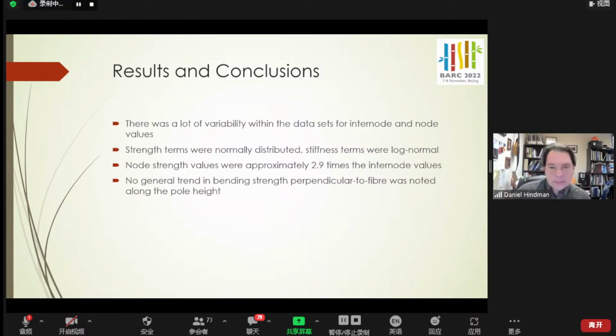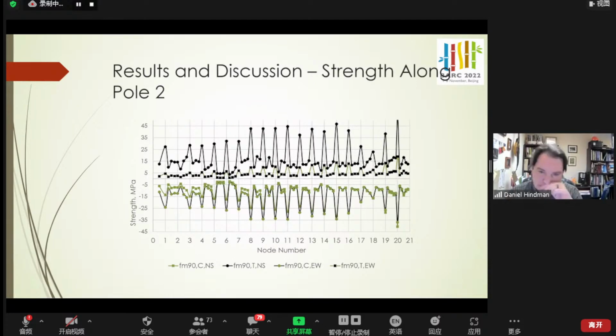And we did not really see a generalized trend in bending strength perpendicular to fiber along the pole height. If I go back to that image, and if you look at, for instance, the black circles, starting on the left-hand side of this graph would be the bottom of the pole, and the right side would be the top of the pole. There may be a generalized trend, but you can see there's actually more variation between the nodes sometimes than along the length of the pole.